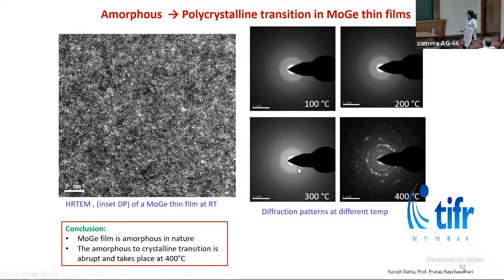We can see that till 300 degrees centigrade, the diffraction patterns are diffuse. That means the film is still amorphous. When it was heated to 400 degrees centigrade, we could see a polycrystalline ring kind of diffraction pattern, which showed that the film has turned into a polycrystalline sample.